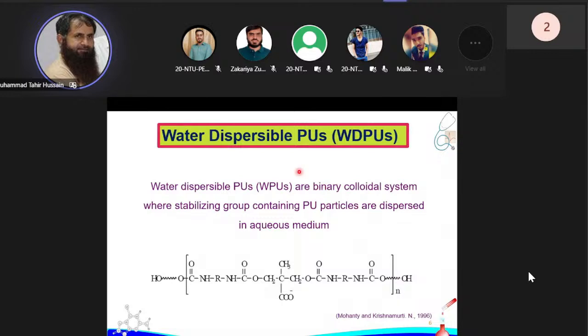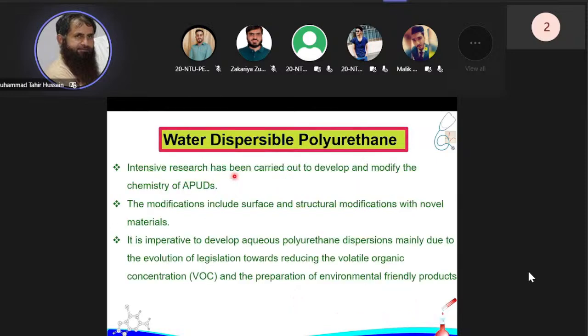So what are the water dispersible polyurethanes? These are binary colloidal systems where stabilizing group containing PU particles are dispersed in an aqueous medium, in which some ionic groups are present that help to disperse the material into the water. Here, there are some carboxylate groups on the polymer that help to disperse the material into the water. Intensive research has been carried out to develop and modify the chemistry of APUDs. The modification includes surface and structural modification with novel materials. It is imperative to develop aqueous polyurethane dispersions mainly due to the evolution of legislation toward reducing volatile organic content and the preparation of environmentally friendly products.